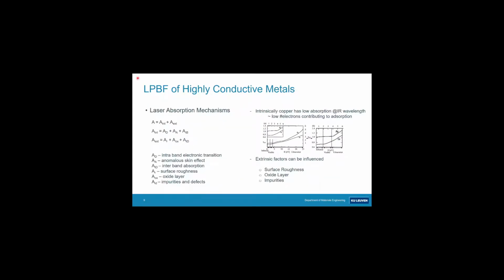So if we look at how such a material interacts with the laser beam, there are intrinsic and extrinsic parameters contributing to absorption phenomena of a material in general. The intrinsic ones are labeled here. There are intraband electronic transitions and interband transitions, which are purely related intrinsically to the band structure of a metallic lattice. There is also the anomalous skin effect. And then the extrinsic properties are, for example, the surface roughness of a plate or also of a powder. Its oxidation state: if a copper oxide layer with another absorption behavior is present, of course, it will increase the absorptivity. And all kinds of impurities and defects at the surface will also influence the absorption behavior.